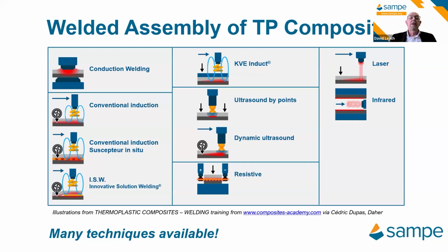Then there's various ultrasonic techniques, just a local kind of what you might consider a spot welding. But there's also quite a lot of work on moving dynamic ultrasound to join long joints together. Then there's resistance welding. Again, with carbon fiber, you can actually apply a current directly to the carbon fibers and allow them to heat up. Or you can put a metallic susceptor in and apply the resistive current that way as well. And then direct heating methods of the areas to be joined, such as laser or even infrared. So we certainly have many different techniques available.